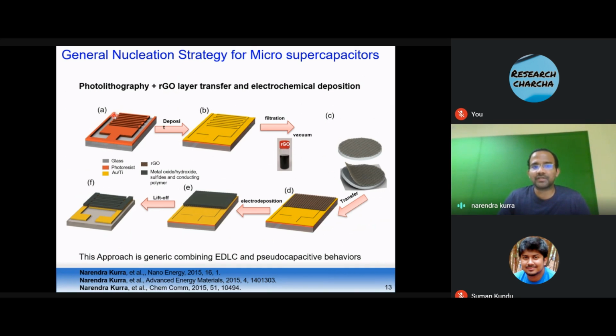Again, we have this photoresist which was exposed and developed, and then we did metallization, titanium and gold. At this stage, we have made this freestanding graphene oxide film, reduced graphene oxide film, on top of an anodic aluminum membrane, and this membrane was dissolved away in base solution. We get the freestanding, floating reduced graphene oxide film, which was further transferred onto the substrate as shown here. And here now this RGO layer, reduced graphene oxide layer, can act as a nucleating layer for the deposition